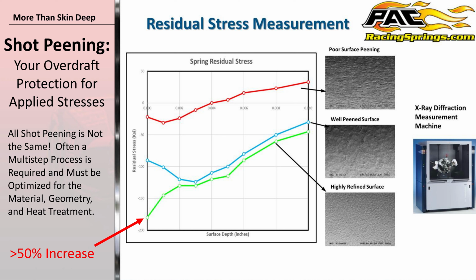But you can see that red line up on the top, that's a normal peening. Up to about 4 thousandths, it's given us some good, but past 4 thousandths, it sort of messed us up a little bit, damaged it. But you get really good at doing these peening, you get more like the blue line. And you can see it's lower at the top, and the reason it's lower at the top is because that damaged the peening cost. It's made it rougher up there.